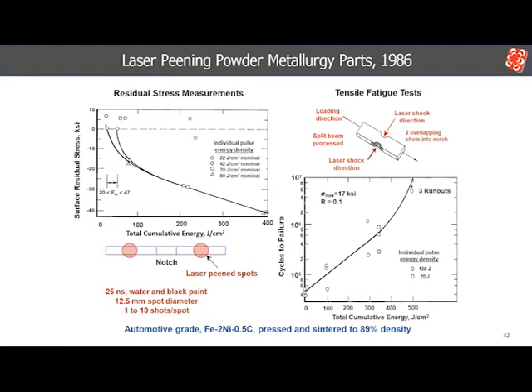The laser peening was directly into the notches on each side of the specimens. The fatigue life improved dramatically with increasing shots. 5 shots at 100 joules per square centimeter energy density produced an increase of more than 2 orders of magnitude in fatigue life. However, their deal for a powder metal company did not work out.